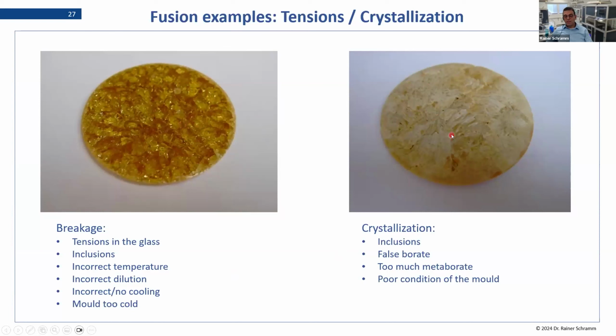So if you have crystallization, you can imagine that your fusion recipe is not optimal. So your melt is not able to form a glass. The crystallization is much quicker in the cooling process. And this means that you have either too much metaborate, or you have a very poor mold, so that you have a lot of crystallization starting points in your mold. So this could be all reasons. While when you have then more tetraborate, you again become a glass.